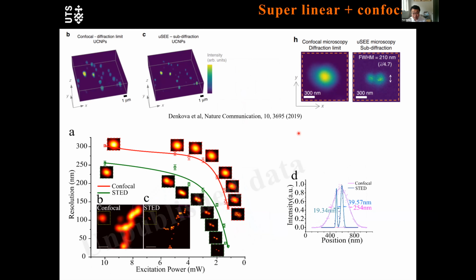And in the same year, 2019, both our group and Nisa's group published papers experimentally showing this kind of effect. It shows that if we put these particles inside a living cell and select the pumping laser in a certain range, they can directly resolve some features here. So they can directly see super-resolution imaging, but the resolution is not that good, only 200 nanometers, but it's already super-resolution. And for us, we saw the same thing. Once we decrease the excitation laser to match the condition, we see that the resolution of the image can go down to about 130 nanometers.